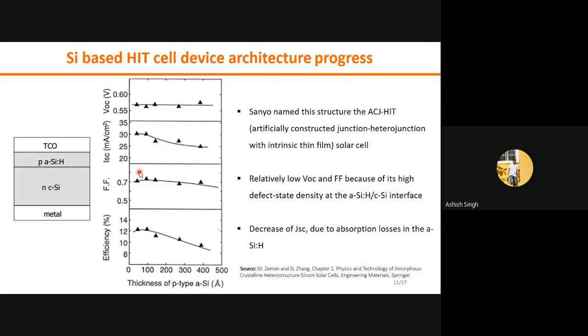But it is important to notice that the current density was getting down with increasing thickness of the hole transport layer, but the VOC was stable and fill factor was also stable. But the VOC is significantly poor, and current density and fill factor are also poor. So to find out the reason behind that, they analyzed and found that due to the surface interface defects, there is a high defect state density at the interface of N-type crystalline silicon and P-type amorphous silicon. VOC is getting down because of the surface recombination. And the current density decrease is because of the parasitic absorption with increasing thickness of amorphous silicon.